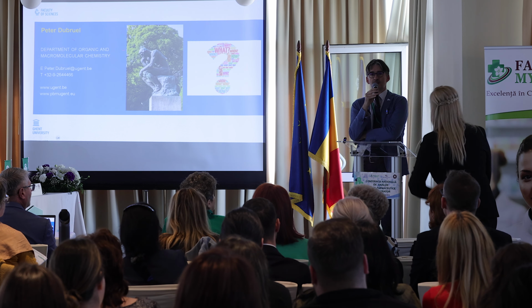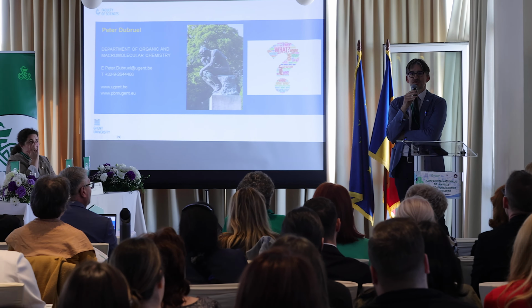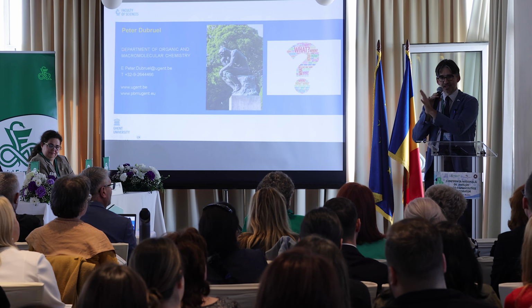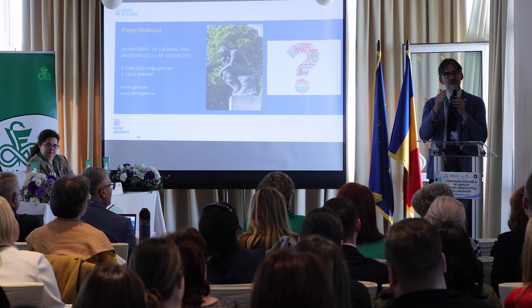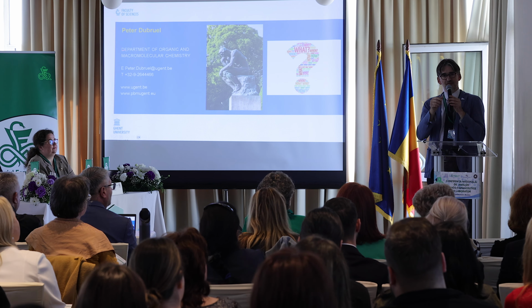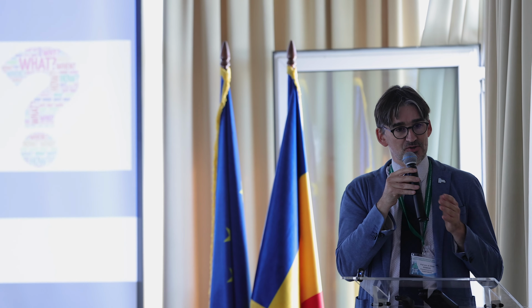Yeah, good point. Synthetic polymers are the most easy polymers to electrospin. Any student that starts in our lab, we give polycaprolactone, 80,000 grams per mole. They run to the lab and that works fine. From the moment you deviate from polymers that are perfect fiber-forming polymers, like some synthetic, but also some biopolymers, a detailed optimization is required. But having said that, in our lab, but also worldwide, polymers like gelatin, collagen, alginate, and others have already been spun as such. So that's good news.